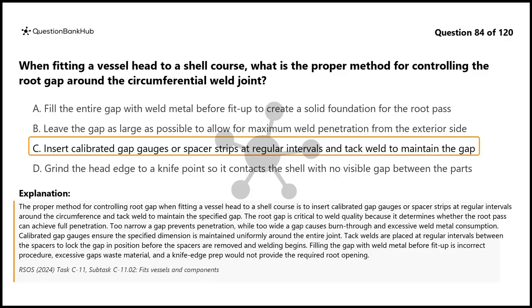The proper method for controlling root gap when fitting a vessel head to a shell course is to insert calibrated gap gauges or spacer strips at regular intervals around the circumference and tack weld to maintain the specified gap. The root gap is critical to weld quality because it determines whether the root pass can achieve full penetration. Too narrow a gap prevents penetration, while too wide a gap causes burn-through and excessive weld metal consumption. Calibrated gap gauges ensure the specified dimension is maintained uniformly around the entire joint.